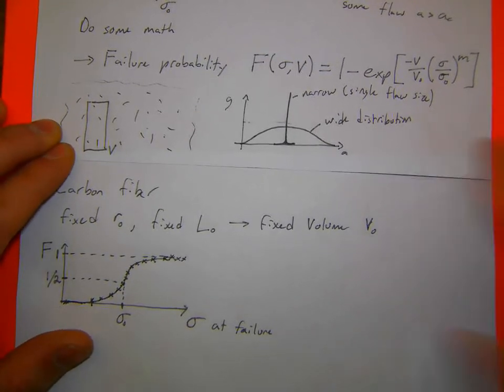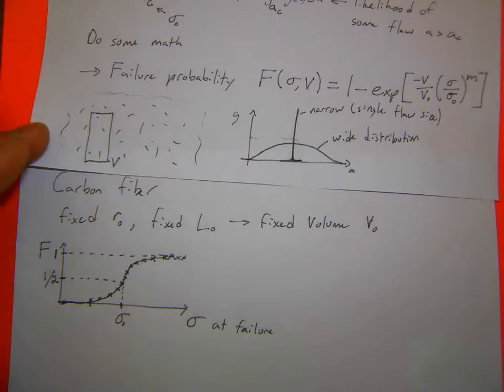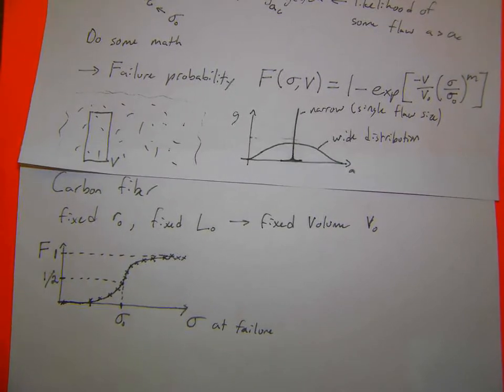To some degree, but a lot less so, because this is a good question. In your tension experiments, some of the parts failed at slightly different yield strengths, and some had different ultimate strengths. There's a reason for that, and that reason is the distribution of initial imperfections in your materials. But in a ductile material, because after the initiation of failure you have a lot of plasticity, you see it manifest as slight variations in the exact yield strength. So an initial flaw doesn't necessarily cause catastrophic failure. It can if it's really big and you have that a_c beyond the critical stress for fracture for the material.